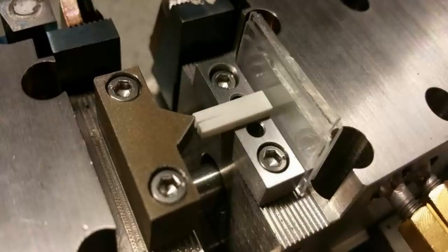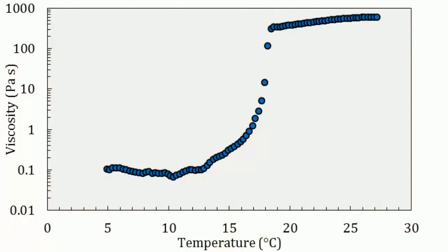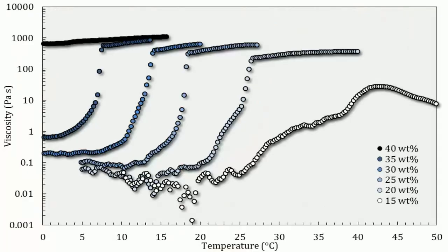The source even attempts to quantify this printability using ratios of these properties. Trying to put a number on it. Yeah, they found that a good paste needs a high storage modulus, G prime, and a high yield stress relative to how much it deforms under stress. Basically, stiff and strong relative to its tendency to flow.